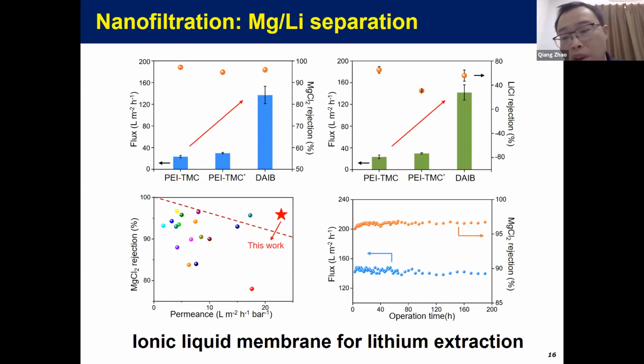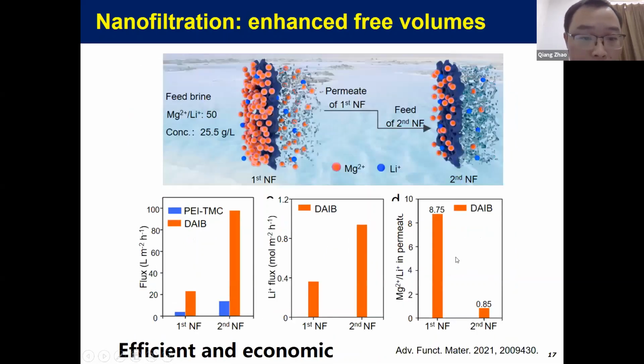What's more important, as we know, is that those membranes, although they give high flux, are susceptible to high pressure or operation time. But here, the flux is stable versus operation time, which indicates its practical potential for high pressure applications. Then we set up a 2-cycle operation for magnesium and lithium separation. By doing so, we are able to reduce the magnesium to lithium ratio from 50 to about 1 or 2, combined with very high permeability using this membrane. So I think it indicates efficient and economic advantages of this membrane.